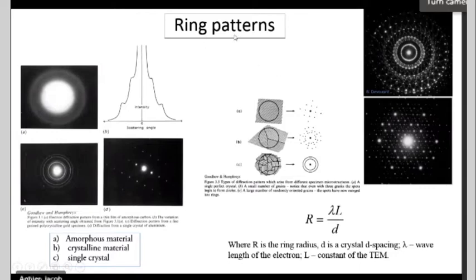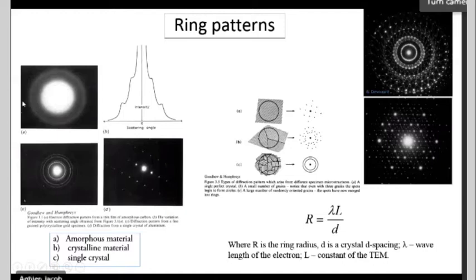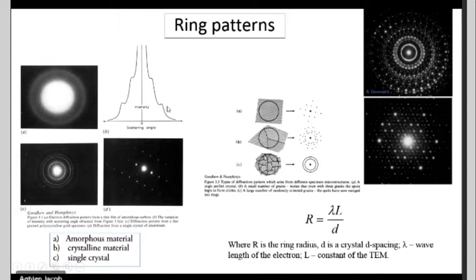Looking at diffraction patterns, you will encounter different types. Image A shows a diffused ring — the diffraction pattern of amorphous carbon. If you have an amorphous material, this is its signature or fingerprint. You can calculate the intensity profile with respect to scattering angle. From this intensity profile, you can calculate the pair distribution function (PDF) — a very powerful tool for amorphous or glassy materials. PDF is the probability of finding an atom at a position relative to another atom.